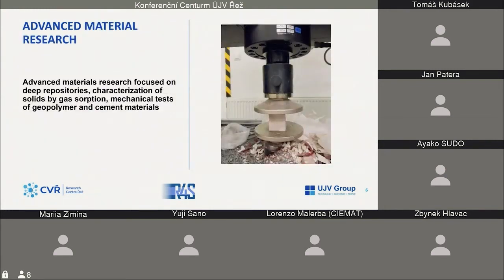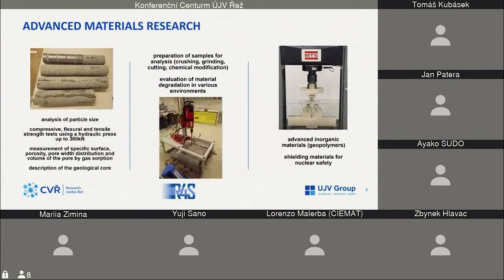The second part of our research focused on the deep repository is our advanced material research. We are providing characterization of solids by gas sorption and mechanical tests of geopolymers and cement materials. In our laboratory, we are able to analyze particle size, perform compressive, flexural and tensile strength tests using a hydraulic press, measure specific surface, porosity, pore width distribution and pore volume by gas sorption, and describe the geological core. Together with that, we prepare the samples for many analyses, like crushing, grinding, cutting, or other chemical modification.